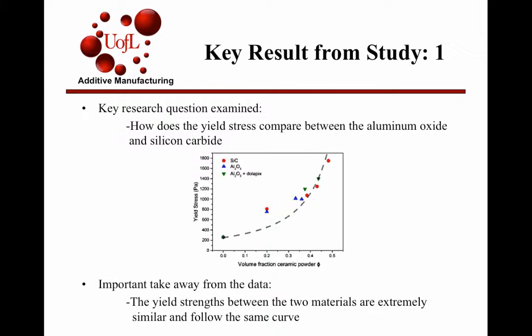For the yield stress, as you can see, they plotted both the aluminum oxide and the silicon carbide here. The testing parts were bars, 40 millimeters long by 3 millimeters by 2 millimeters. Basically what they saw was that the aluminum oxide and the silicon carbide were very similar. They added Dolapix to the aluminum oxide because they believed it would electrosterically stabilize it. They thought it would make it a little bit stronger, which it did a little bit, but it didn't really help too much. They added 0.5% weight of Dolapix to it.